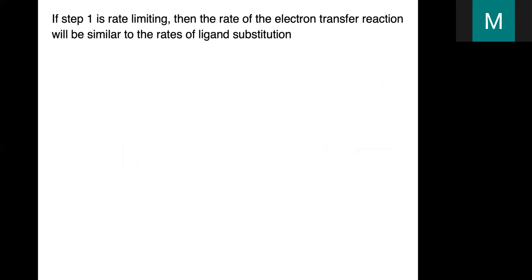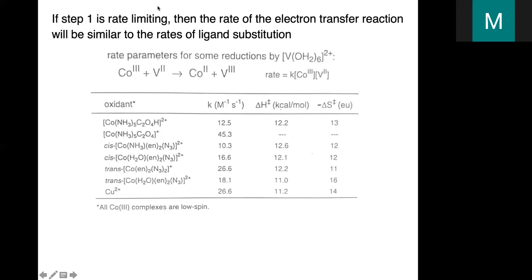So let's just look at some situations where each of those scenarios is thought to be occurring. And so, we should note that if step 1 is rate limiting, then it should be the case that the rate of the electron transfer reaction will be similar to the rates of ligand substitution. And so here we have some examples where this appears to be the case. These are reactions where we're starting with cobalt-3, an inert complex. We've got 5 ammonia ligands, or ethylene diamine and ammonia ligands. And then there is, in each of these cases, a bridge forming